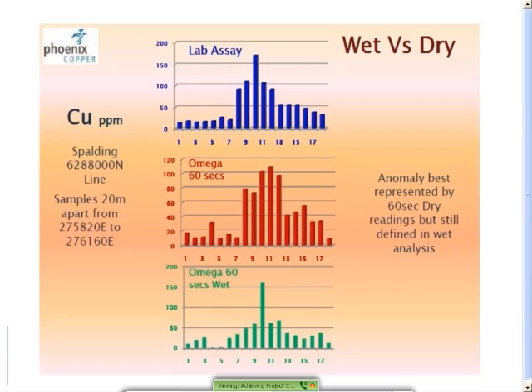In addition, the analyzer assumes parts per million or percent dry weight. So with water in a sample, the mass of the sample is increased, which dilutes the total concentration of the target element. This is clear in these slides, where the green graph reports lower values. However, fortunately for Phoenix Copper, the anomaly remains defined.